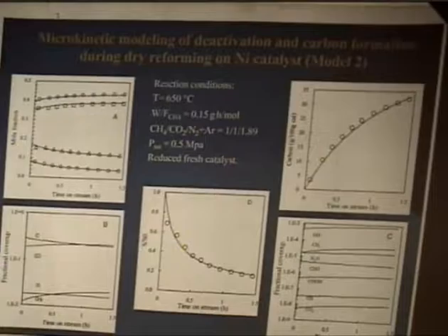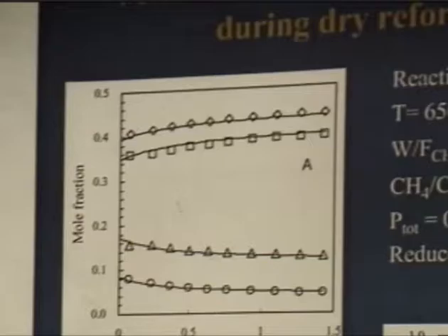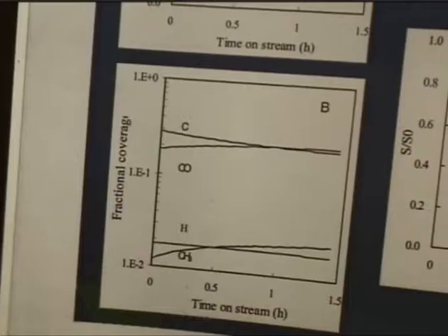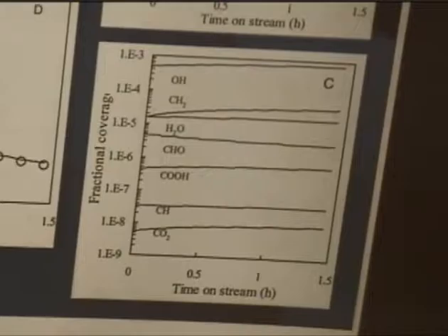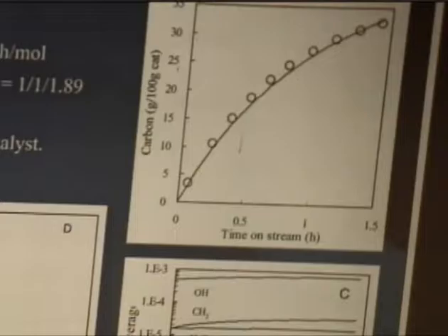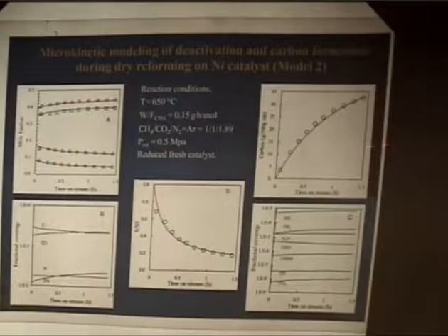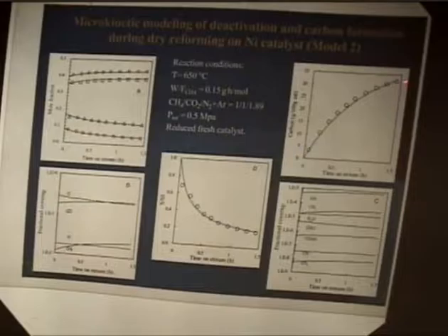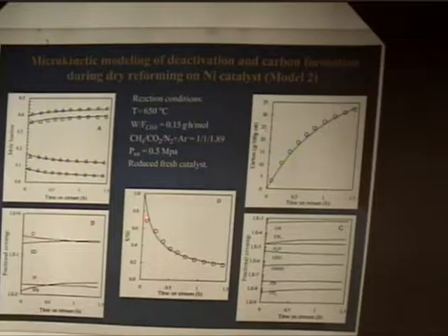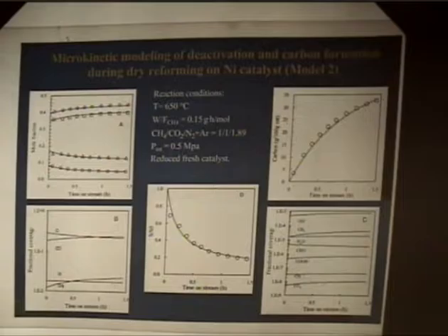this is some of our results with this microkinetic modeling of the deactivation by carbon formation with driving force kinetics. And they are using exactly the same parameters as I showed before. We have good fits for the gas phase reactions, and of course we have the results from our earlier work. This is the reduction in surface area, either caused by sintering or caused by encapsulating carbon.